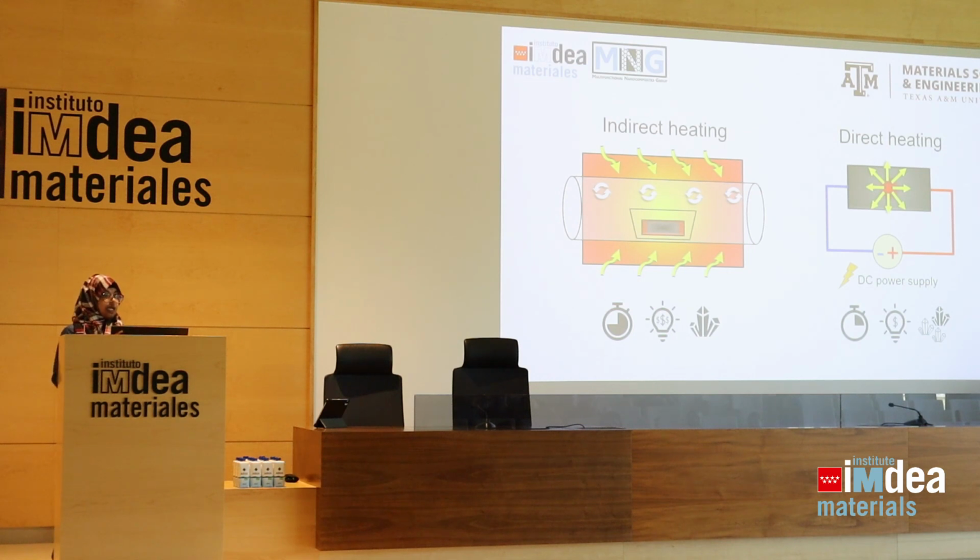Also, due to the limited time, you get smaller crystallite sizes, which means larger surface area. And this is ideal for applications like catalysis and charge transfer in battery electrodes. So what does all this mean? Our simple processing technique can be used for similar composites with a conductive network to save time, energy, and to get unique crystal structures. All you need to do is provide electricity, and what you end up with is the final heat-treated material. The decarbonization future is to electrify, and I believe that includes materials processing.